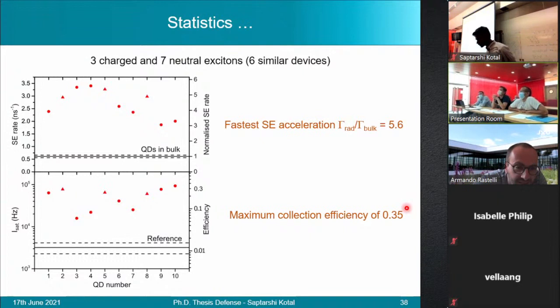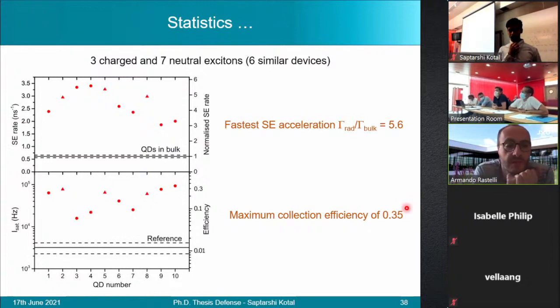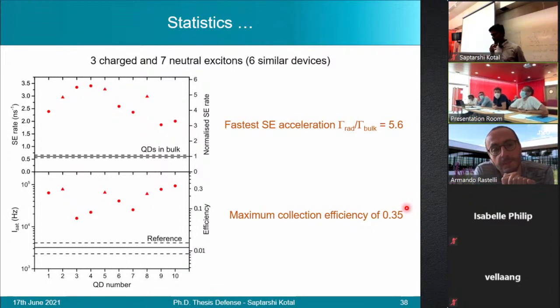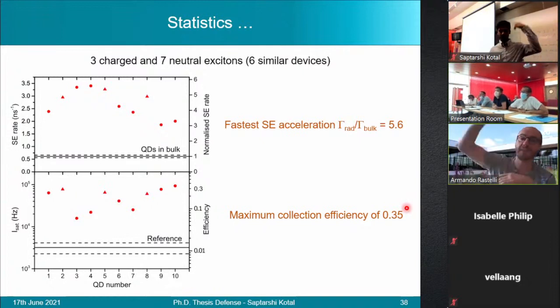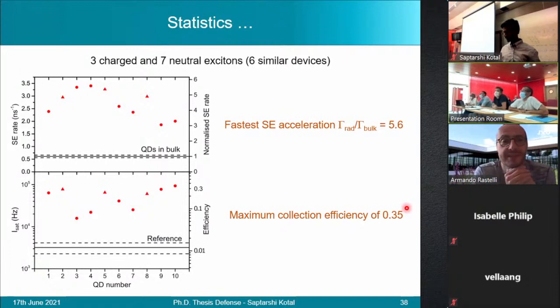For the moment, we generally are finding pretty much a similar trend, except for one or two dots. If we have a high saturation intensity, we also see a relatively good acceleration. There are 2 points, the dots 3 and 4. They have high rate, but low saturation intensity. This could be an indication, for instance, of non-radiative decay. Yes, it could, but precisely on these dots... No, I understood that you would expect then some dot very fast and even beyond.